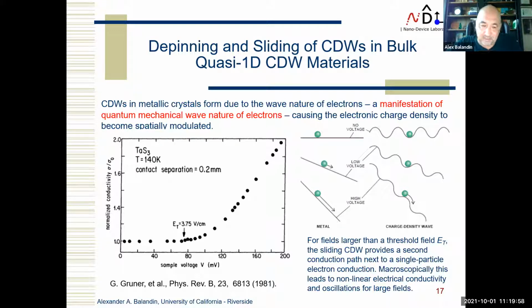I would like to emphasize here that this is actually a quantum mechanical state, a quantum phenomenon, because this is a manifestation of the wave nature of electrons in order to create this modulation in charge density. It's also many electrons condensing to the state, so it's a many-body phenomenon. So now what was happening in typical experiments? If you start applying bias, initially you have a little current, and this current is just the current of individual electrons because the charge density wave is pinned. But at a threshold field, the wave starts to slide. As a result, you have this nonlinear current conduction, a strong increase in current, and simultaneously you also have an AC component in current. So you'll have some oscillations. You can illustrate it with some models. If you look at the left, no voltage applied. So regular metal, you can use this charge density wave.